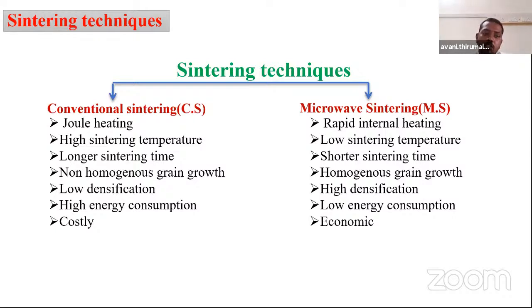I will explain. Normally, conventional sintering follows Joule heating, but microwave sintering follows rapid internal heating. Conventional sintering requires high sintering temperatures and longer dwell times compared to microwave sintering, because in microwave sintering the electromagnetic radiation interacts directly with the ceramic samples. Inside, all the dipoles oscillate and generate heat. Due to that heat, it sinters. It requires a much lower sintering temperature and less dwell time. For that reason, ceramic materials are sintered at low temperatures. Due to this, we avoid the volatilization of the lead in microwave sintering.